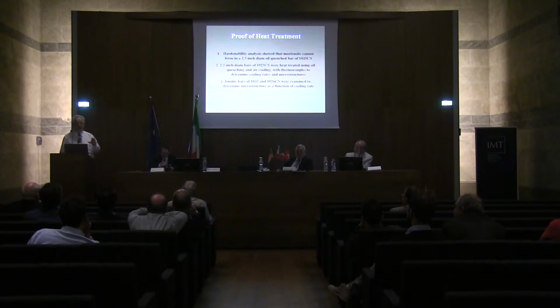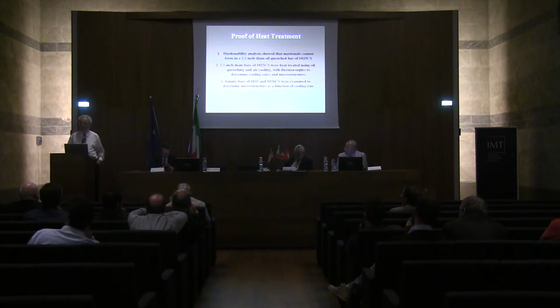Now, he took the data that the watchman had as to when he saw the Aeolian vibrations, and he went through the entire weather data for the 289 days the tower was up. And he looked at the same orientation for the wind and the same speed. And he estimated the total amount of time that the tower could have had these dynamic loadings from the Aeolian vibrations. And his estimate of service life was 300 days, which is damn close to 289.